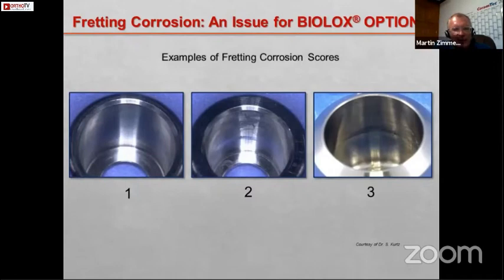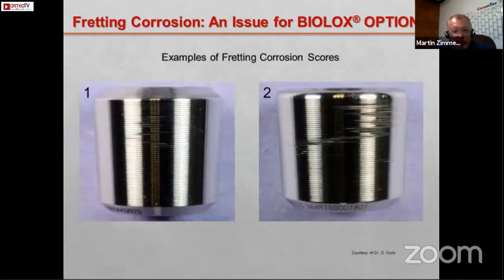First of all, some examples of fretting corrosion scores from the interface between the stem taper and the taper inside of the sleeve. So on the left-hand side, one, no fretting corrosion, mild and moderate. That's what they can find. And if you look on the outside of the sleeve, that means now in contact with the ceramic ball head, only 2 levels of fretting corrosion have been observed. No fretting corrosion on the left side and the mild one.